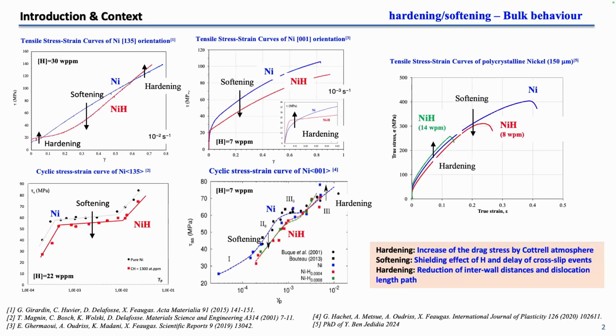We start by presenting some results on the bulk behavior. In the past, for single orientation here, or for multi-slip orientation single crystal, we have shown that when you add hydrogen, we have softening but hardening, hardening in this place and here softening, and in the early stage of the deformation, hardening. And we have the same results for cyclic stress-strain curves, and the results of École des Mines, the David Delafosse group, and also our group on multiple slips show that we have softening and hardening, which depend on the plastic strain amplitude imposed.